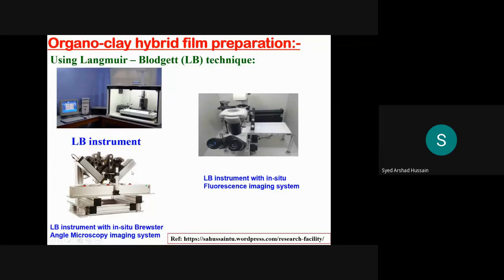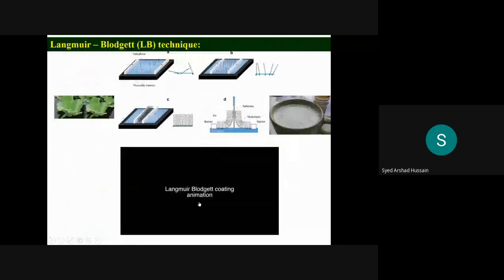Here, light is allowed to fall at the Brewster angle for the air-water interface, and at that point, all the light is transmitted through the surface. But if some material is there, then the refractive index changes and the Brewster angle changes. So some light is reflected back, and one can catch this reflected light using this detector, and this is proportional to the arrangement of the material, so one can have an indirect idea about the organization of the floating material. So these instruments are available in our lab.